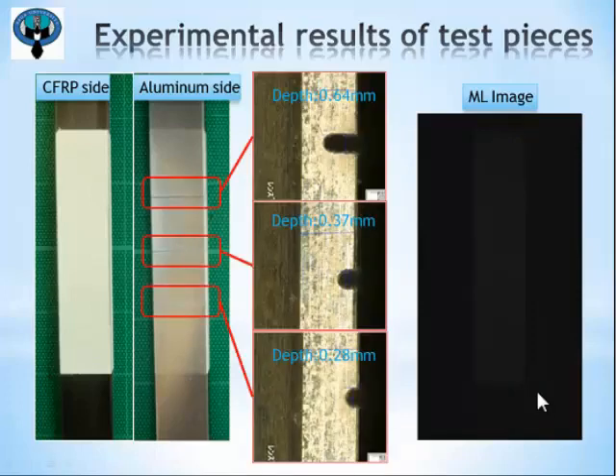At first, we examined ML pattern by composite test piece. The test piece is composed of CFRP layer and aluminum plate with 3 notches. The ML sensor was painted on the surface of CFRP layer. The depths of the notches are 0.64, 0.37 and 0.28 millimeter respectively.